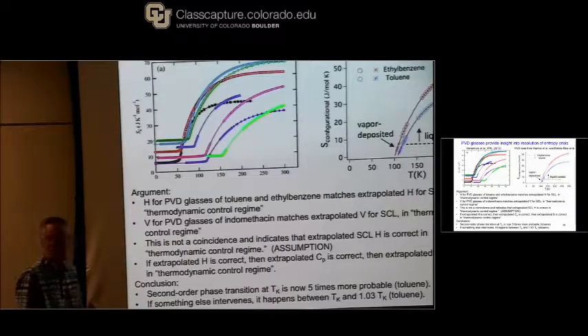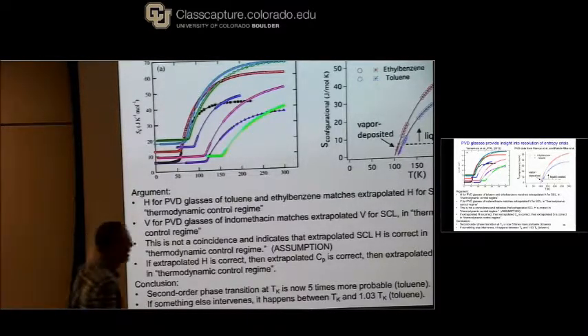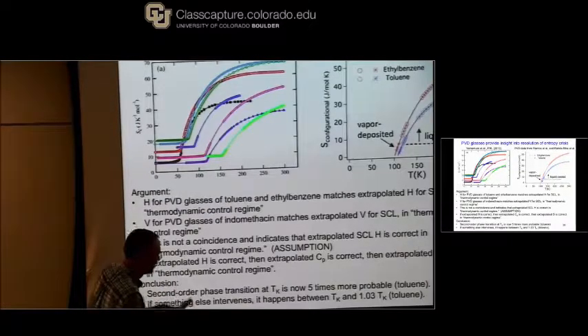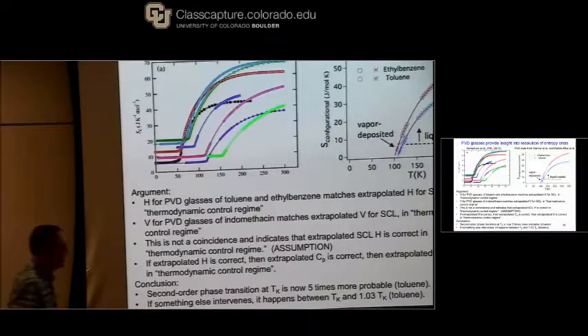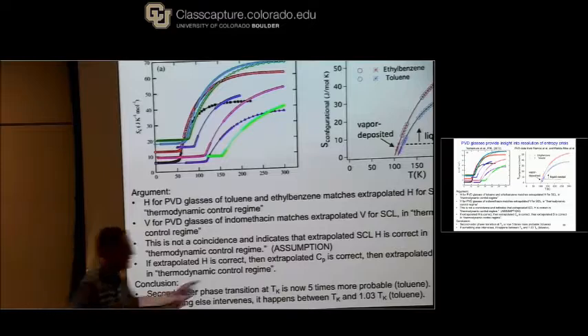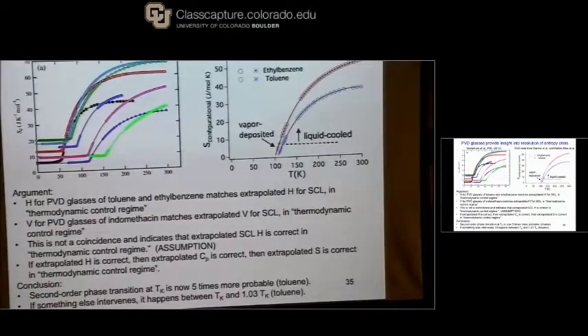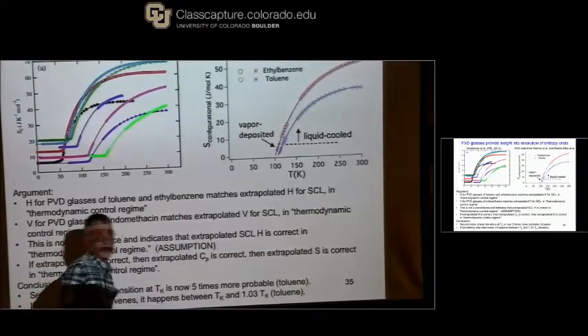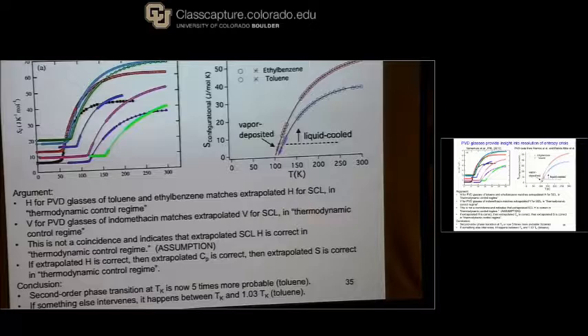Okay, so I think this is not a coincidence. I think this indicates that the extrapolation of the supercooled liquid enthalpy is correct. That is, since the vapor deposited materials are giving the same enthalpy as the extrapolation is giving, I am going to assume that the extrapolated enthalpy is correct. That's the assumption. Okay, now we go back to being rigorous. If the extrapolated enthalpy is correct, then the extrapolated CP, which is just the derivative of that, is correct. Then the extrapolated S is correct, because it's also just calculated from CP, as long as we're in this thermodynamic control regime.